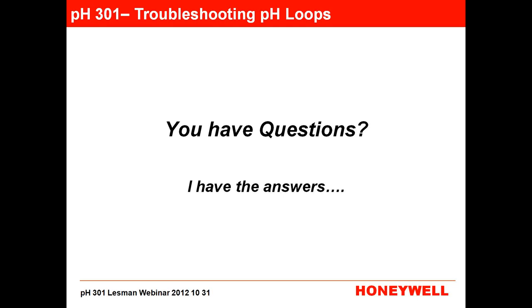Ah, that's a good question. Antimony probes, when you use an antimony sensor, it's because you're down to the last gasp effort. Typically, antimony is used in a process most commonly that has hydrofluoric acid in it. Hydrofluoric acid is an etching solution, and it will etch glass. Like if you get a set of champagne glasses for your anniversary and it has your names carved into it, that's done with hydrofluoric acid. So you can imagine that if you put a device like a pH sensor with a glass measuring electrode, or even a FET, because some of the components of the FET are silica-based, it will take that sensor out. Basically, it just eats off the whole face of the sensor, and then it dies.